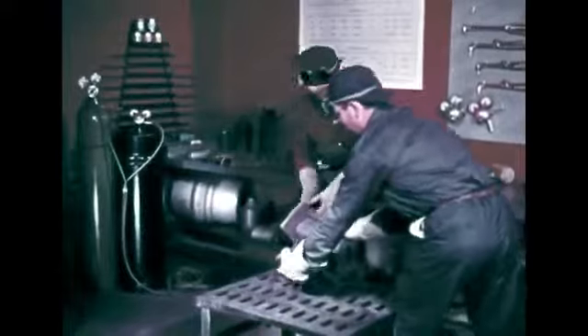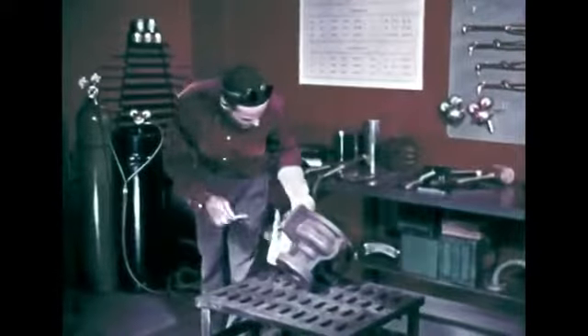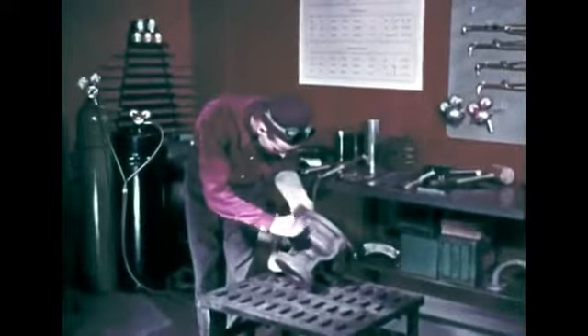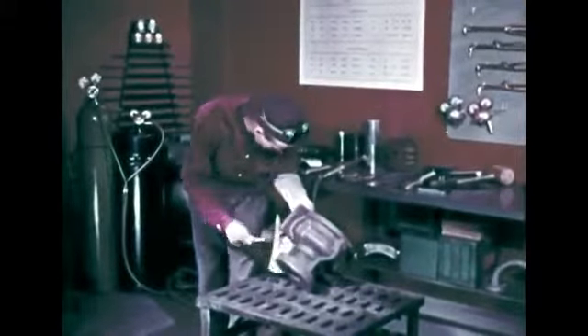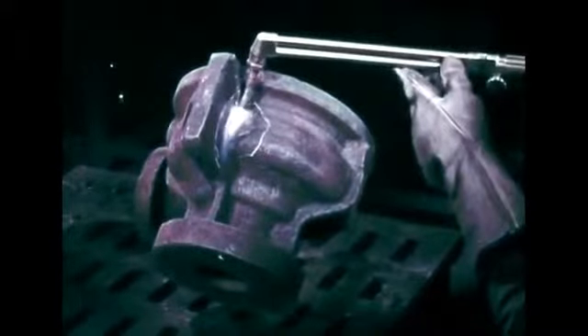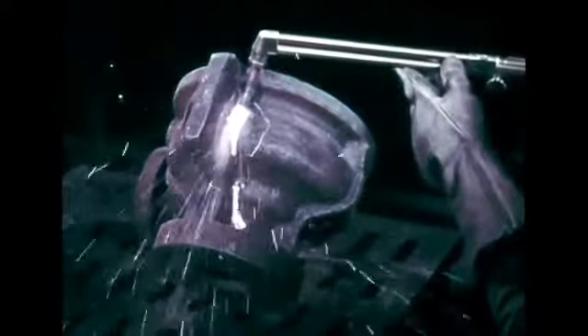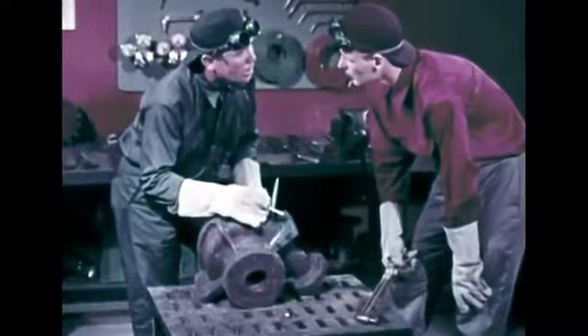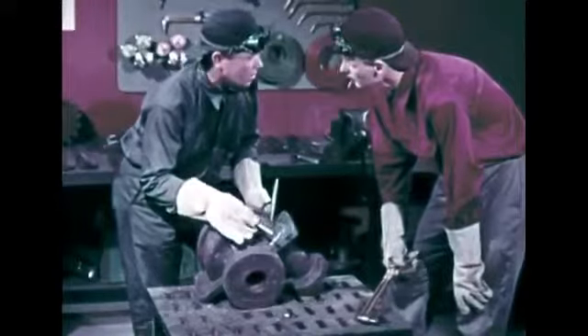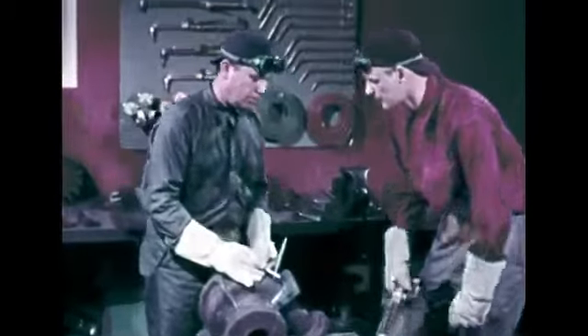You can eliminate slow and expensive chipping or grinding in preparing a cracked steel part for welding. Prepare a V for the weld metal by cutting a groove along the length of the crack. Flame grooving clearly reveals the extent of the crack, so that it is easy for you to tell when you've reached sound metal. That didn't take long. A simple welding job, and it will be as good as new again.